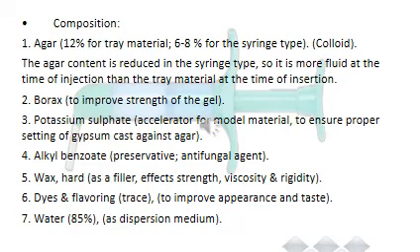Composition. 1. Agar: 12% for tray material, 6 to 8% for the syringe type colloid. The agar content is reduced in the syringe type, so it is more fluid at the time of injection than the tray material at the time of insertion.